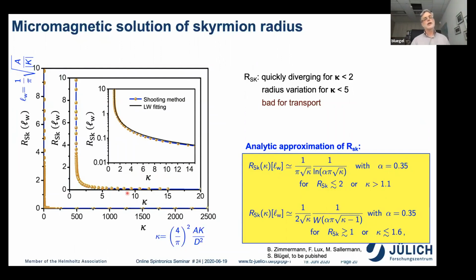Because if you design your material stack such that you are in this regime where things grow quickly, it means that if you have a sputtered sample, you always have fluctuations in your system: fluctuations on DMI, fluctuations of the magnetic anisotropy, maybe a little bit of exchange. And that means you have small fluctuations in this value kappa. But it means you have huge breathing of the Skyrmion radius. And this huge breathing slows you down because now your hard disk, which moves, gains a kind of inertia because it always has to breathe up and down. And this slows the Skyrmion down. So optimally, you would be in this regime.